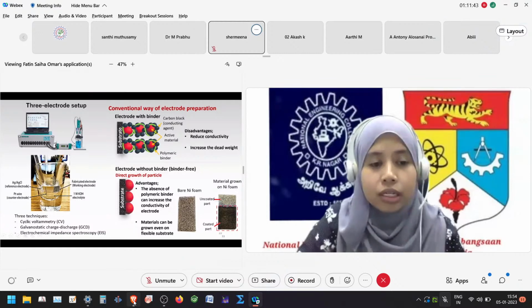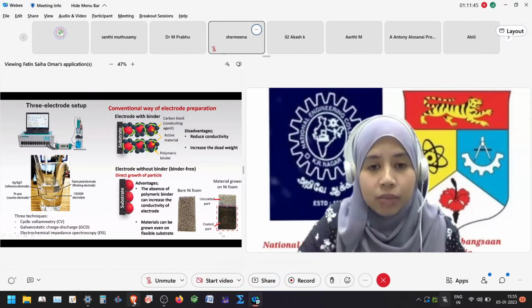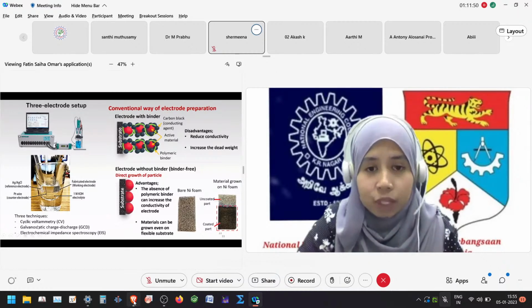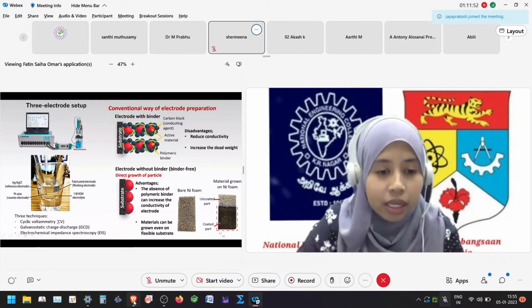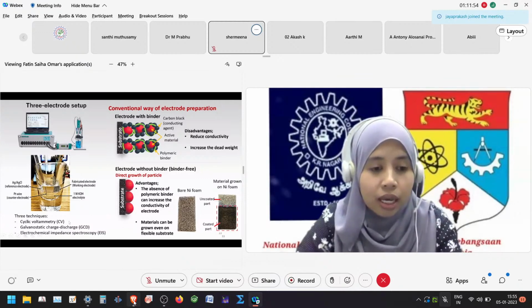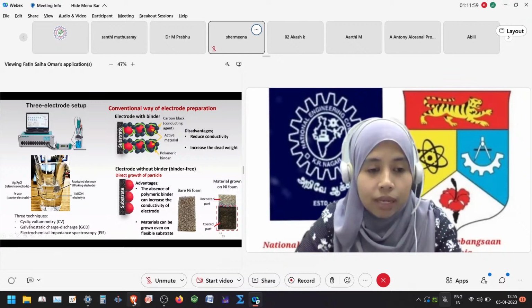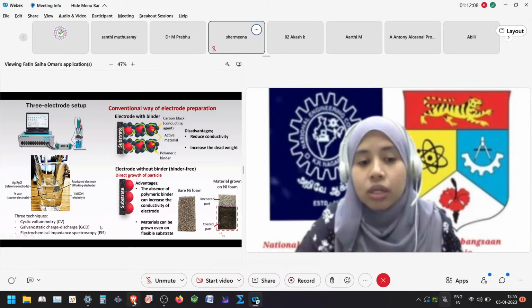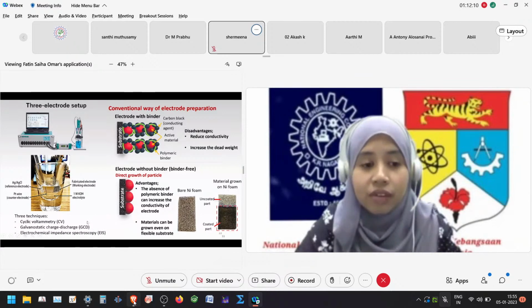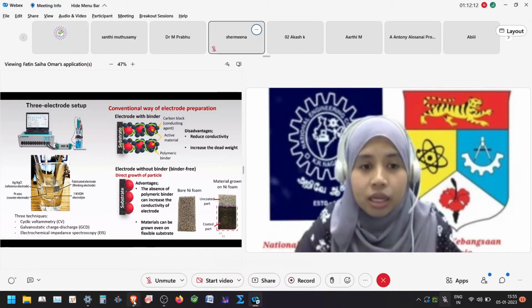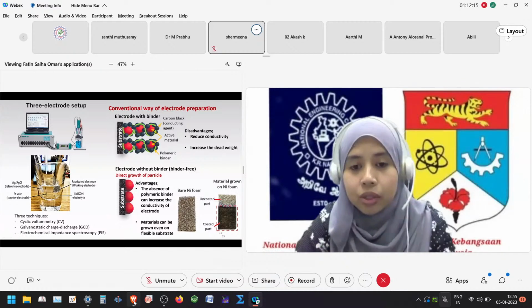And for testing, there are three basic techniques we can use. First is cyclic voltammetry, CV. Second is galvanostatic charge-discharge, GCD. And third is electrochemical impedance spectroscopy. So basically, we can calculate the specific capacity using cyclic voltammetry, CV, and GCD. EIS is used to determine the conductivity or the internal resistance when there is interaction between the electrode and electrolyte ion.